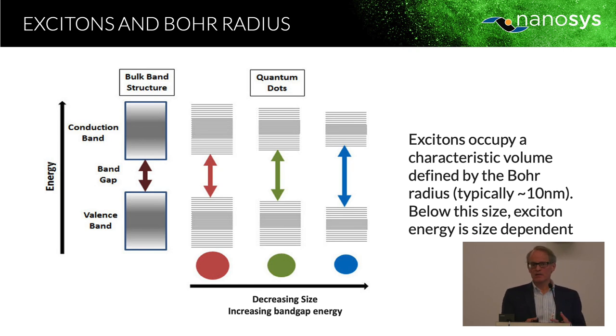One way to think about this is, if you're going to create an excited state in a semiconductor, there's some volume it typically would like to occupy. And if you force it to occupy a volume smaller than that because the particle is just that small, then there's a cost to be paid. This increases the energy of that excited state. So you could imagine if you have a bulk band structure, like is shown on the left in this diagram, imagine that material emits in the near infrared, so out of visible light range, for instance. Then you shrink it down past the Bohr radius, all of a sudden you're increasing the energy, perhaps it now emits in the red. You shrink it down further, raise the energy further, it emits in the green. This is what leads to the tunability that's so valuable in quantum dots.